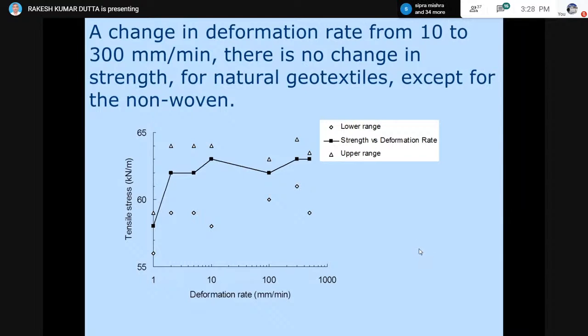So here you see that the rate of strain, which was varied from 10 to 300 mm per minute, and then the tensile strength of the material was measured, and the rate of strain is shown on the x-axis. So here you see that if you see this average curve where my cursor is at present, from this point onward to this one, there is not much change in the strength. Though one of the points is at a lower value, other points are at almost similar range.